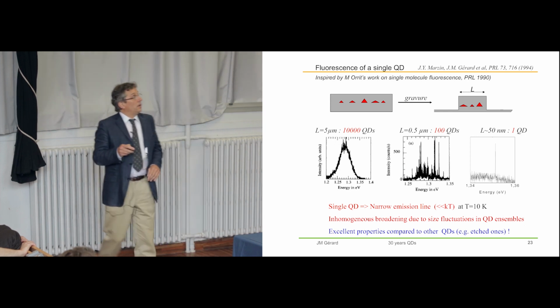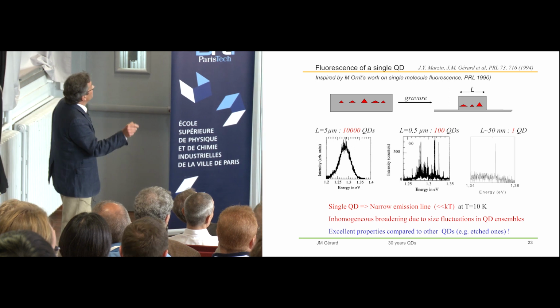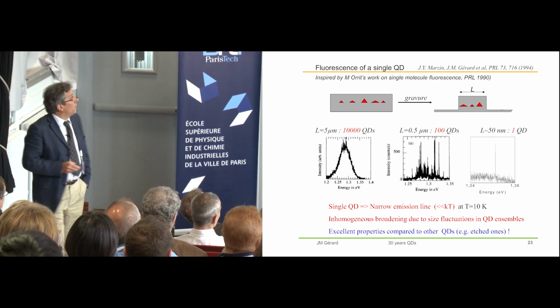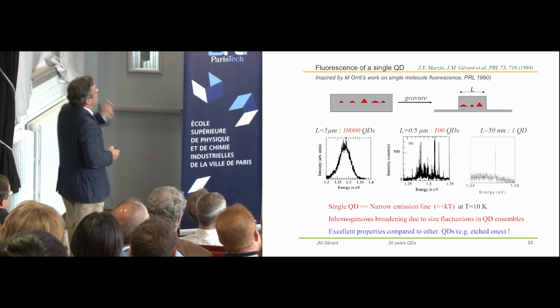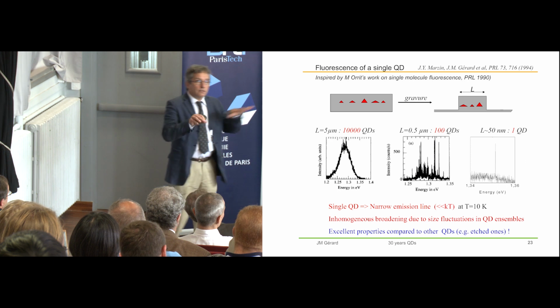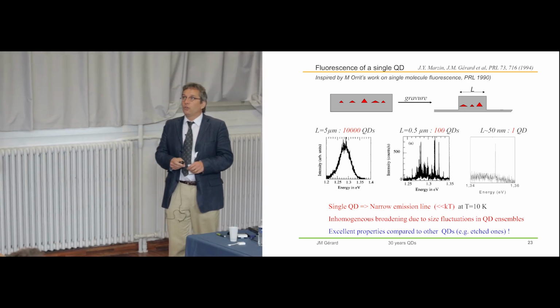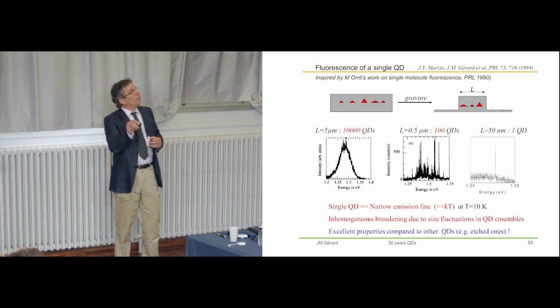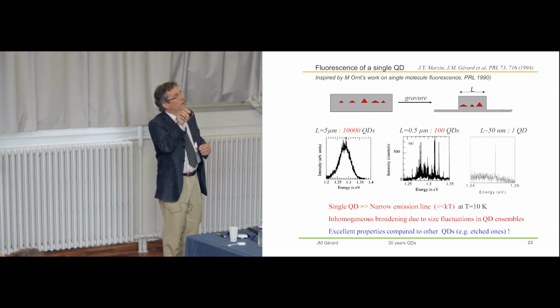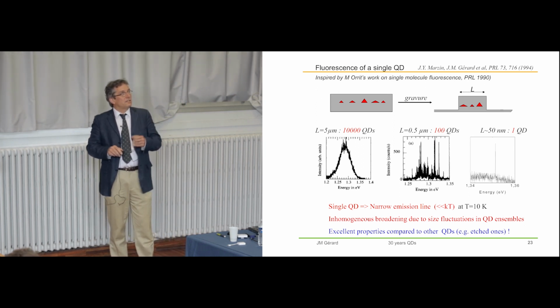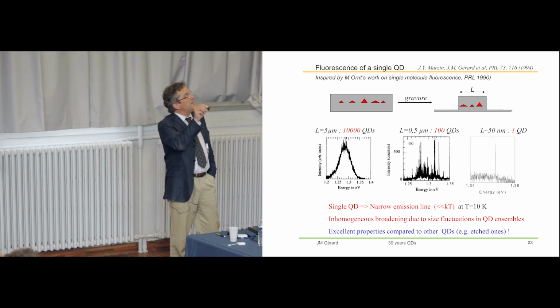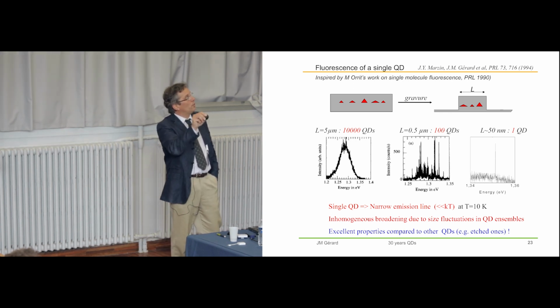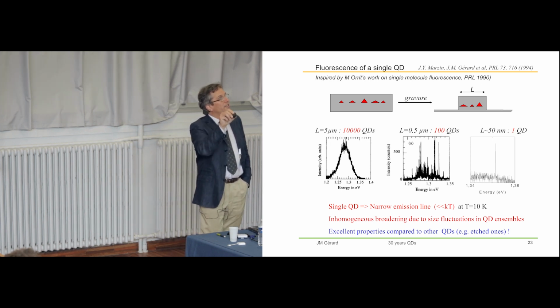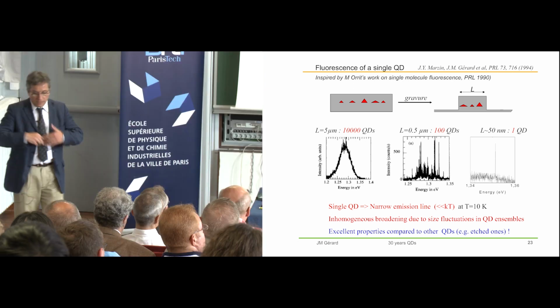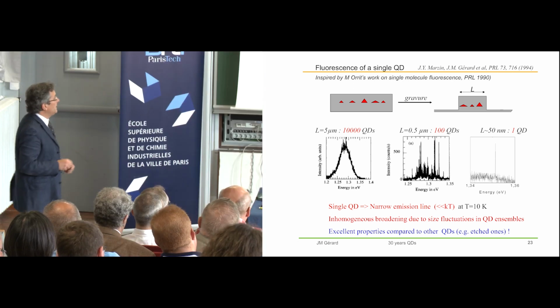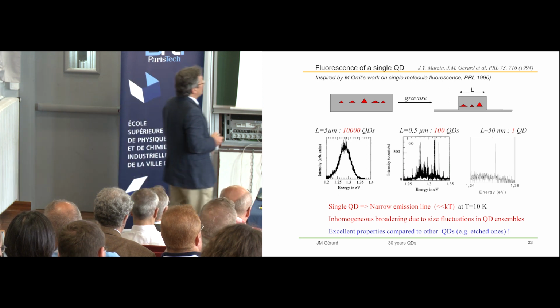So in 94, we did an experiment inspired from Michel Orrit's work on single molecules in order to study the emission from a single dot. In our case, we cannot dilute the quantum dot array that much. So what we did, we decided to reduce the number of quantum dots by selecting a small number of dots in etched mesa structures. And when we move from large mesas containing 10,000 quantum dots, and for which we have a broad line, down to small mesas containing a single dot, we see a drastic change of the emission spectrum. And in the end, we get sharp lines, each related to one single dot.